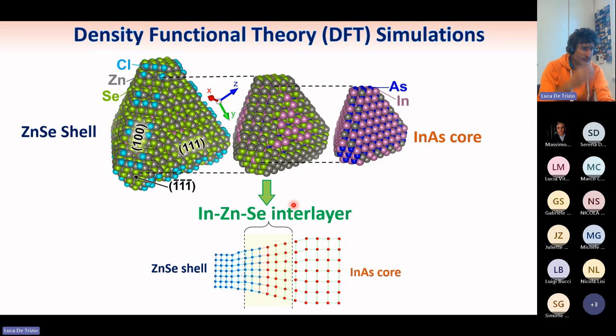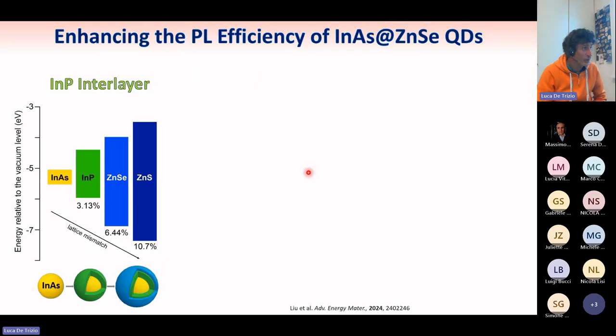And so this is the, say, magic layer capable of making this structure so bright emissive. In yet another work, we tried another different interlayer, not indium zinc selenide anymore. We tried indium phosphide because it features lower lattice mismatch with indium arsenide, as you can see from this sketch.